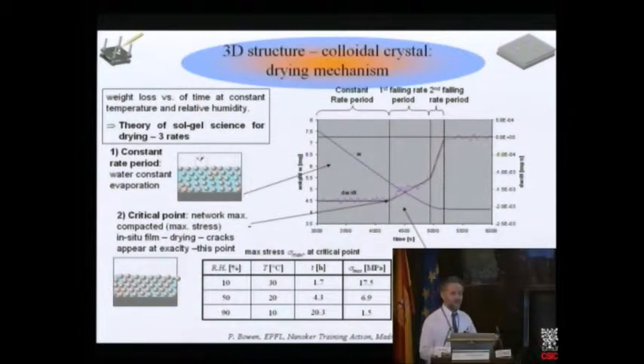So you can go slower, you can go quicker, you can change relative humidity, you can change temperature, you can control the evaporation rate. But you can see that with respect to megapascals, you can get down to about 1.5 without additives. This is not enough to stop these things cracking.